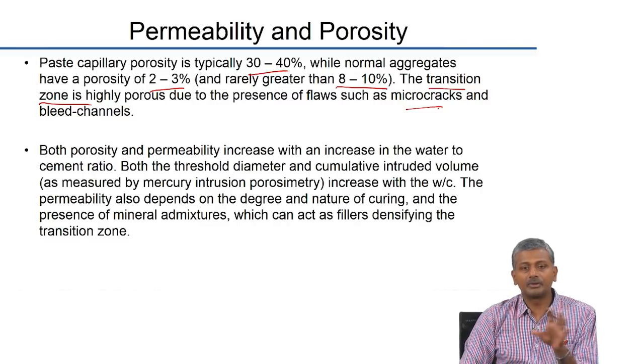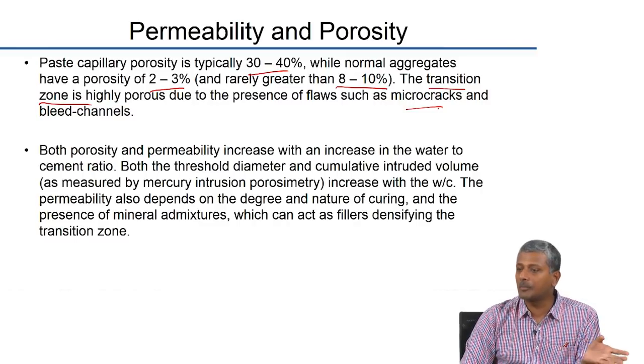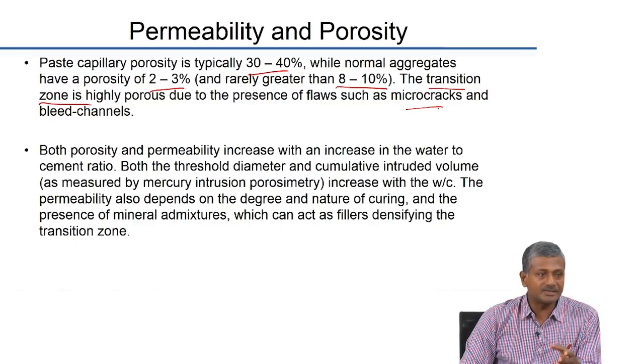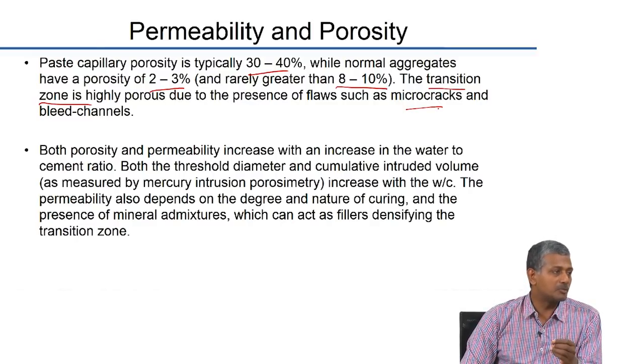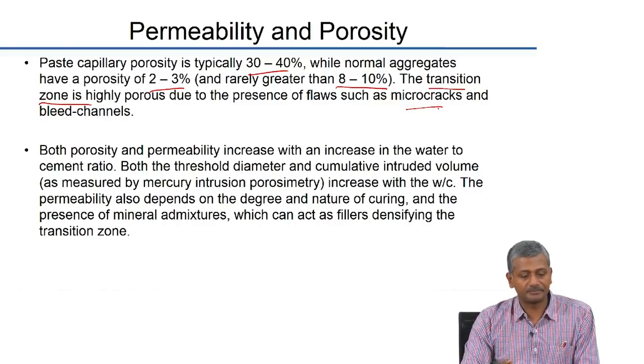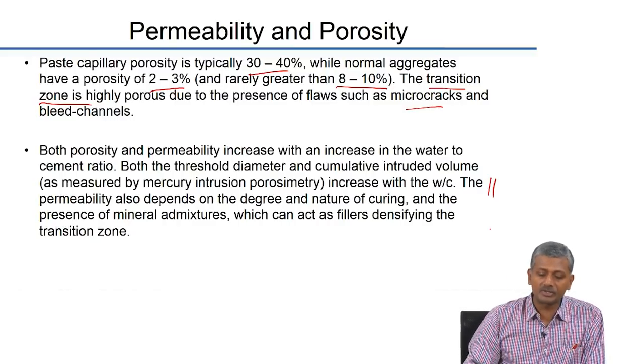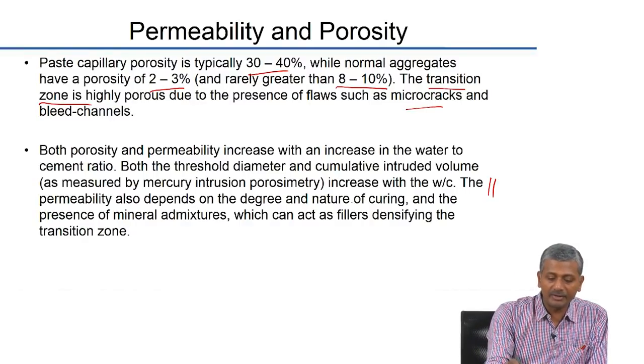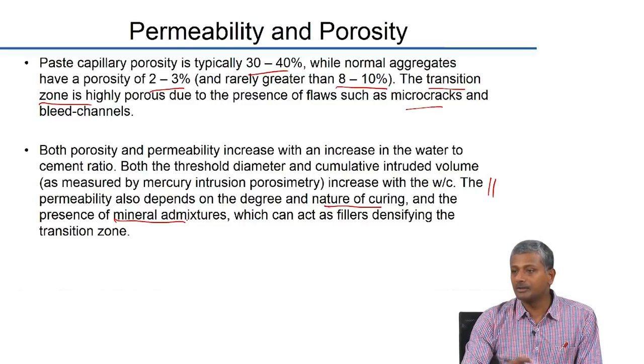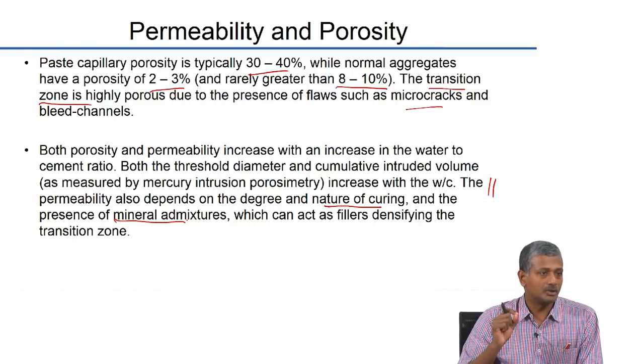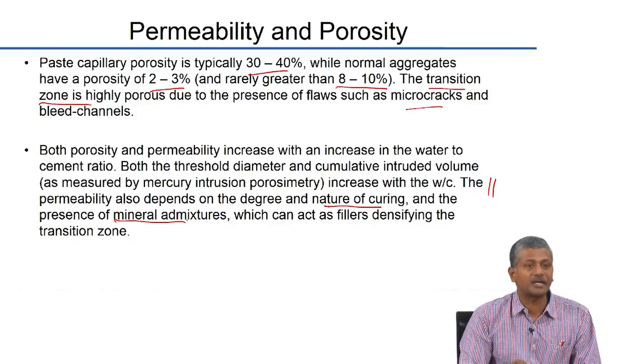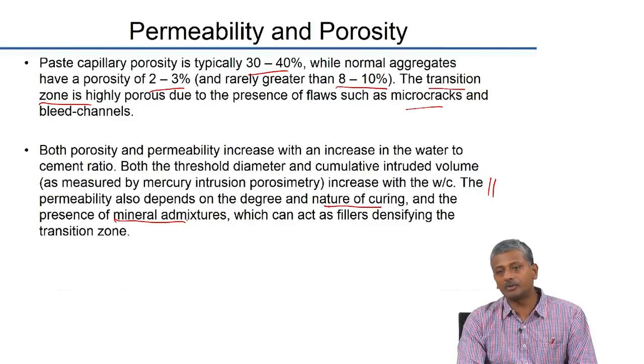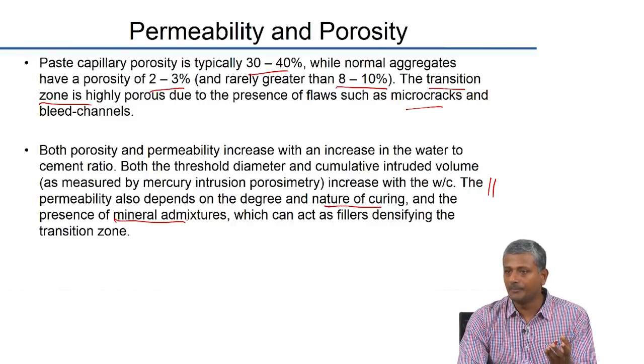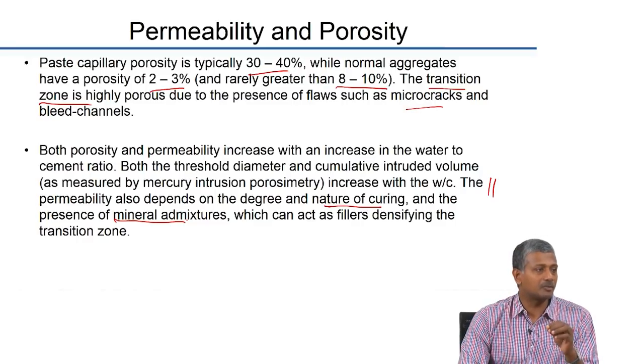Okay. So, capillary porosity in the paste may or may not lead to a high permeability, but the ITZ porosity will definitely lead to high permeability, especially when the ITZ is percolated. And again, water to cement ratio is the primary factor, although you can also have an influence of the nature of curing, the presence of mineral admixtures, especially because they are very fine grained materials that can act as densifiers for the interfacial transition zone. So, whenever you use mineral admixtures, you expect that there is going to be a reduction in your permeability, primarily because of additional CSH that you form, as well as you have additional pore filling because of the fineness of